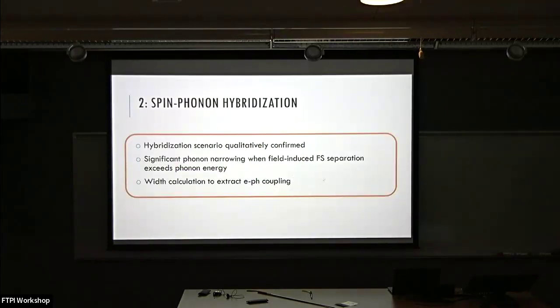So again, to summarize this, I think this field effect qualitatively confirms this hybridization scenario, which means that this Rashba-like coupling is definitely there. The most important effect is this narrowing. And we're working right now, the theorists are trying to do calculations of this field to try to extract the electron-phonon coupling. So once we do that, we will actually be able to tell if it's big enough to cause the pairing. That's kind of it.